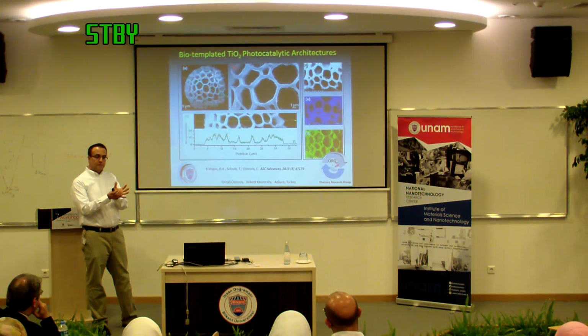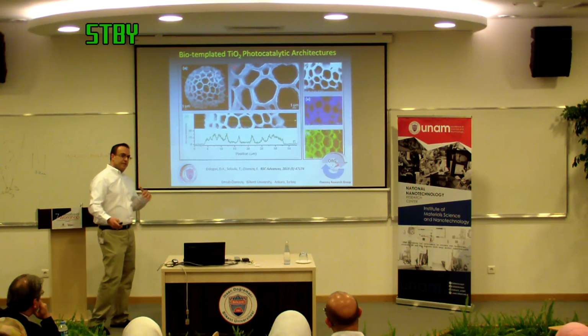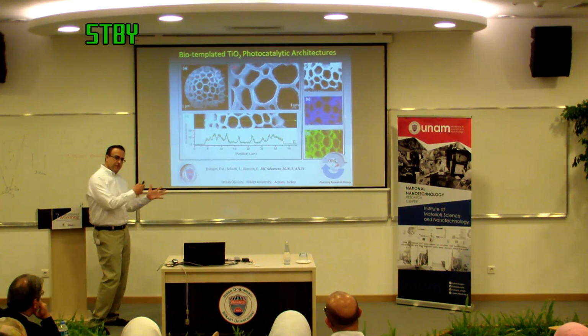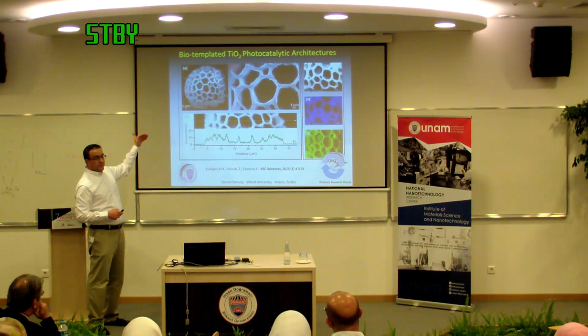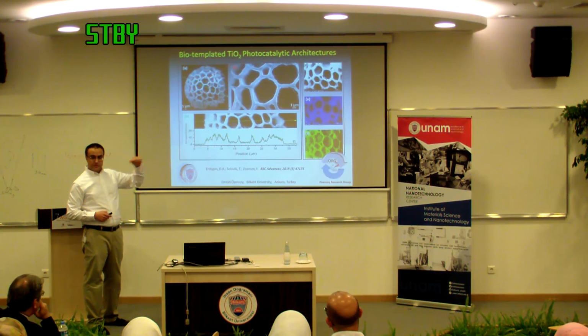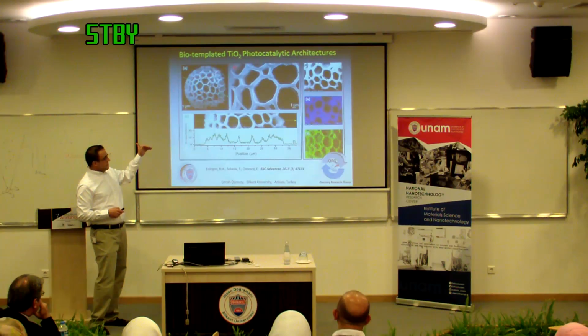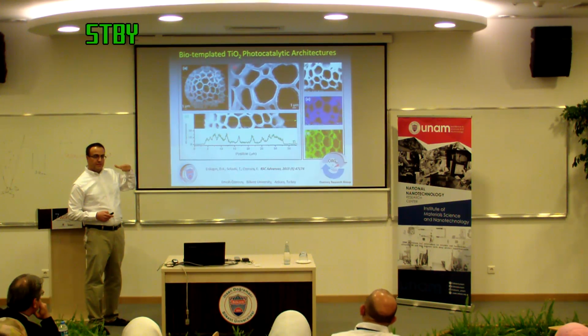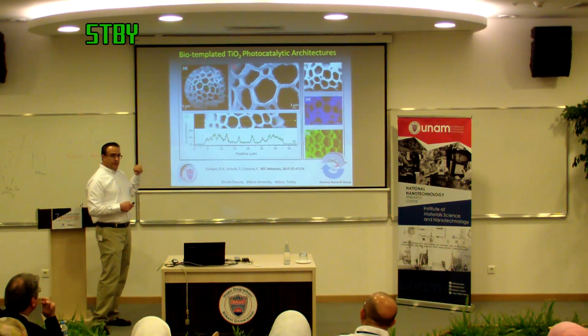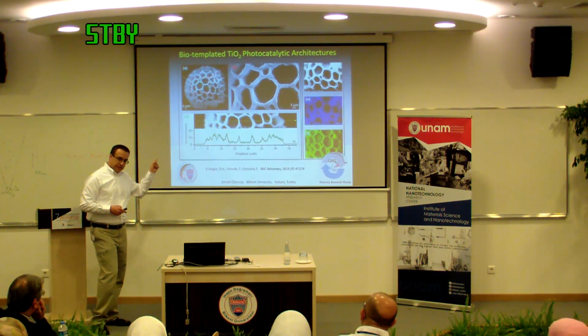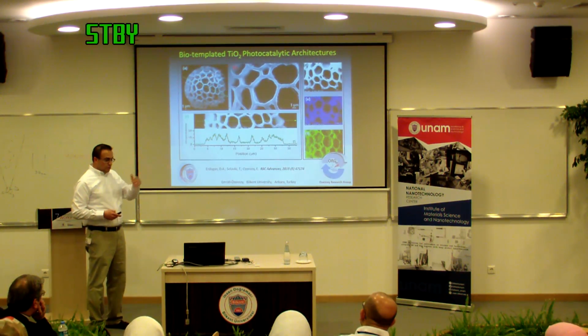Almost impossible to make from bottom-up synthesis. And you can decorate them with quantum dots, plasmonics, other interesting things, so we are working on this one. You can also coat them with graphitic carbon nitride, a 2D material. We have done that too. I'll mention that the thing about graphitic carbon nitride, it's got a band gap of 2.5 eV. It works in visible. So titanium works nicely in UV. It does have also this black issue, but we will talk about some of the problems.